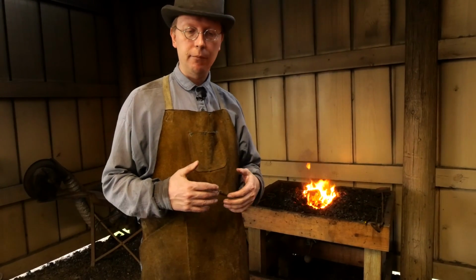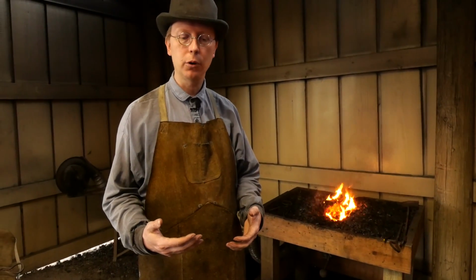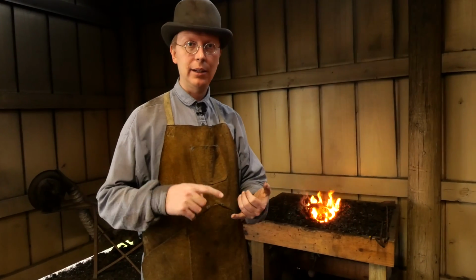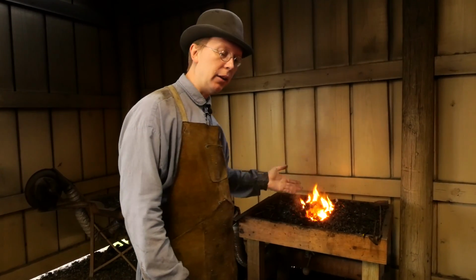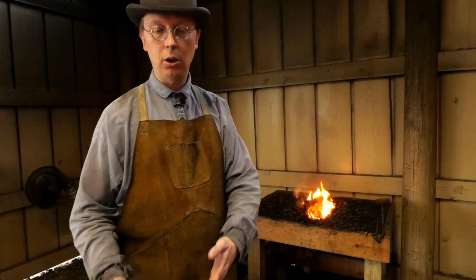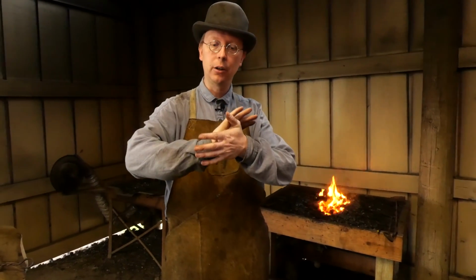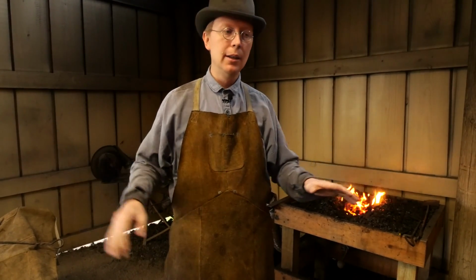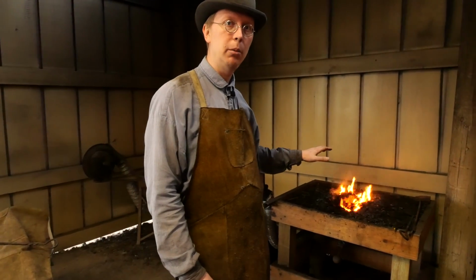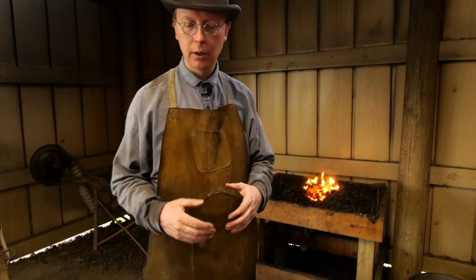of steel. The biggest challenge I really see when people are learning to forge weld that prevents them from getting good forge welds boils down to the steel is either not hot enough when they pull it out of the fire, or they take so long that by the time they hammer it, it's no longer hot enough once those hammer blows come to push it all together, or they hammer it so hard that it just kind of blows everything out. This steel is the hottest we're ever going to be working with it. If you hit it hard, you are really just going to flatten things out and you're potentially going to mess up your forge weld. So we need firm but not super hard taps.